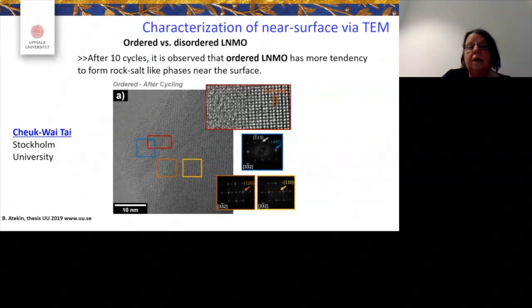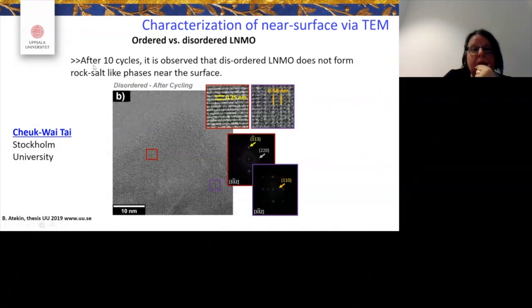But this is not enough. We also went to Stockholm University and did some TEM studies. And if you look at an ordered structure that has cycled 10 times, we see that there is a buildup on the surface of the particle, where we actually see that instead of having this LNMO structure, we get a rock salt structure near the surface. While if we go to the disordered one, after 10 cycles, we don't see this. We see a lot smoother surface.